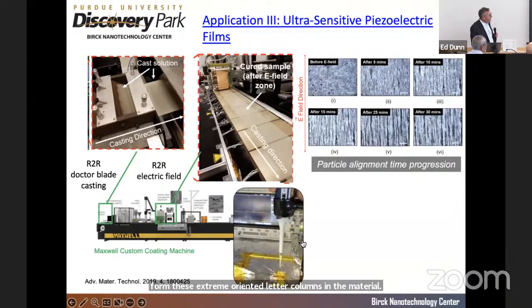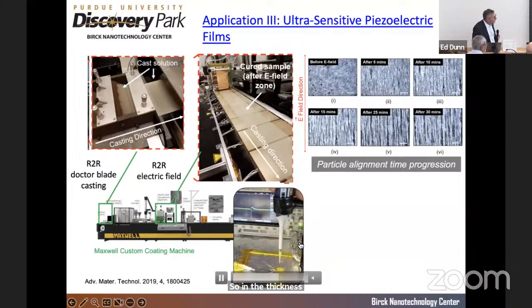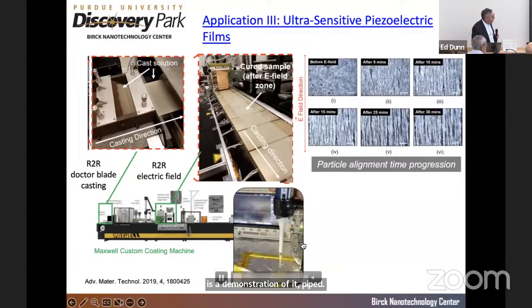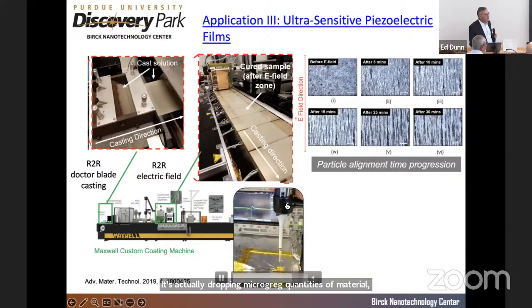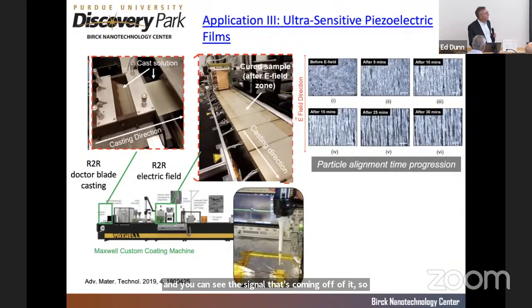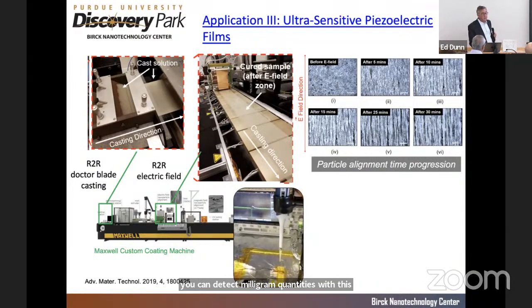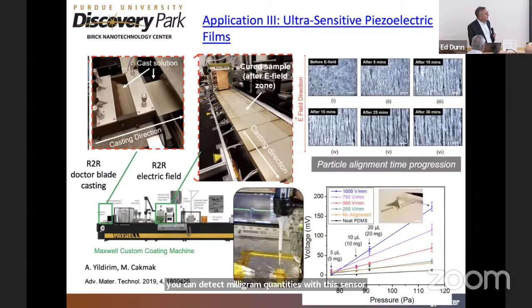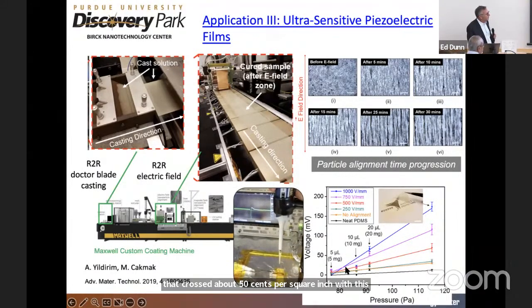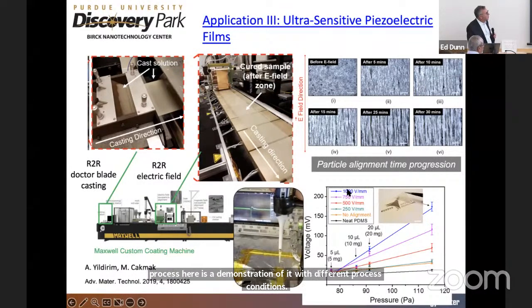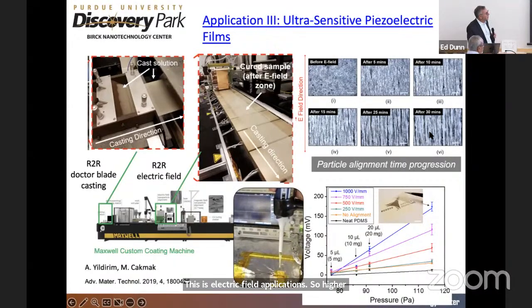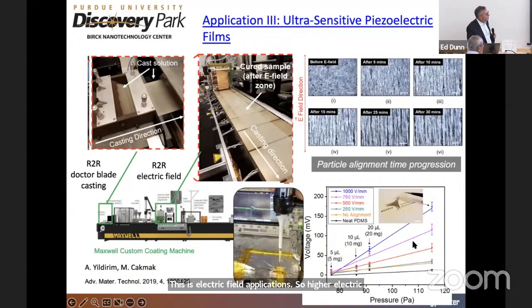So this allows you, here's a demonstration of it. A pipette is actually dropping milligram quantities of material, and you can see the signal that's coming off of it. So you can detect milligram quantities with this sensor. That costs about 50 cents per square inch with this process. Here's a demonstration of it with different process conditions. This is electric field application, so a higher electric field gives you a better organization, and you have a higher sensitivity.